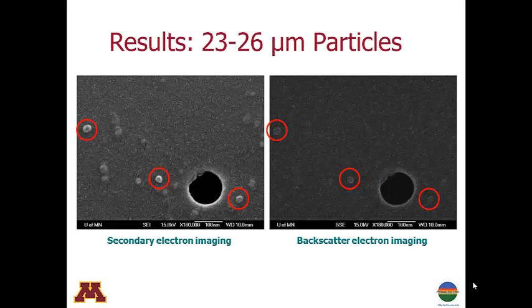For the nanocomposite resin, the smallest particles we could observe using the SEM were those in this image, which were about 23 to 26 nanometers in diameter. On the left is a view of the particles using secondary electron imaging. The particles are easily distinguished from the background substrate. When we look at the same particles using backscatter electron imaging, we would expect the particles to stand out brightly from the polycarbonate substrate if they contained elements like silicon, magnesium, calcium, and aluminum present in the nanoclay. However, they blend into the background, indicating that they are probably composed of the resin itself.